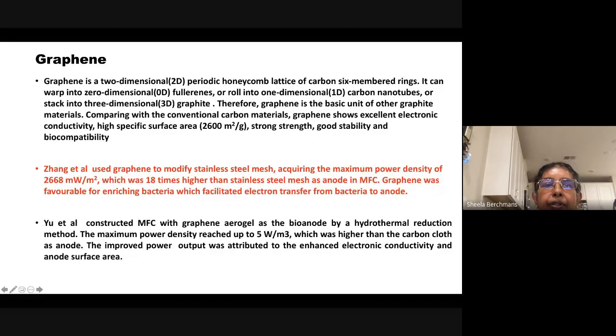So one of the reports where they have used graphene to modify stainless steel mesh reported a maximum power density of 2,668 milliwatts per meter square, which was 18 times higher than stainless steel mesh as anode in MFC. Graphene was favorable for enriching bacteria, which facilitated electron transfer from bacteria to anode.